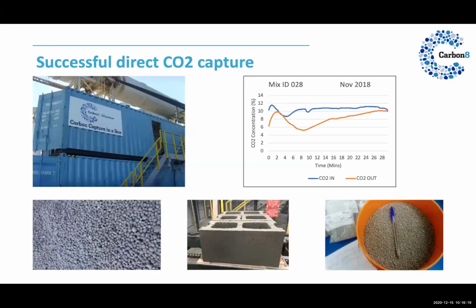So here's a typical graph from a day's run in that demonstration, and you can see the concentration of CO₂ going into the mixer is around that 10%, and going out at the beginning of what is a batch process, you're stripping about 50% of the CO₂ out of the flue gas. Over the 15-20 minutes of the batch, that reactivity is used up, so the concentration of CO₂ going out of the mixer gradually increases.